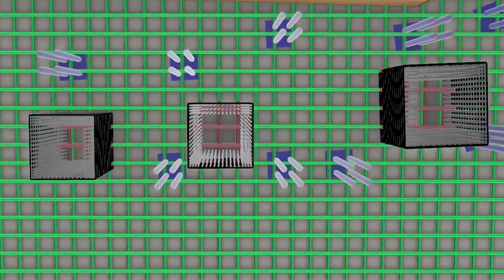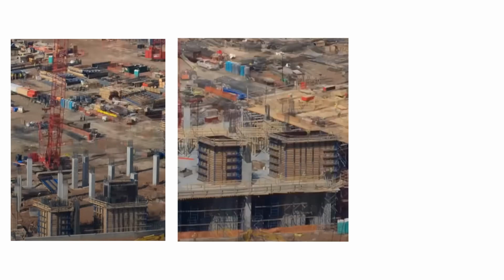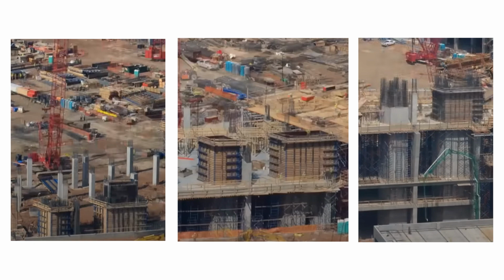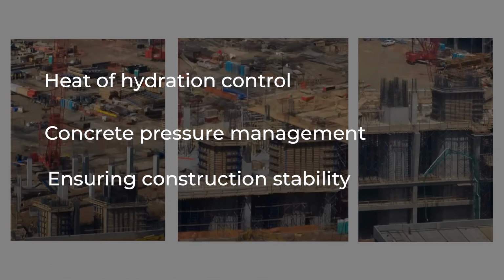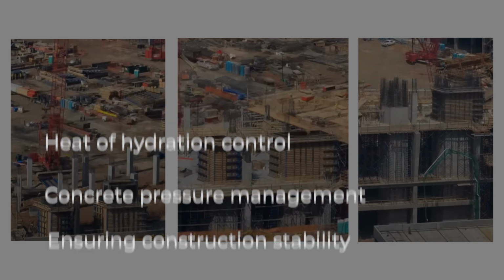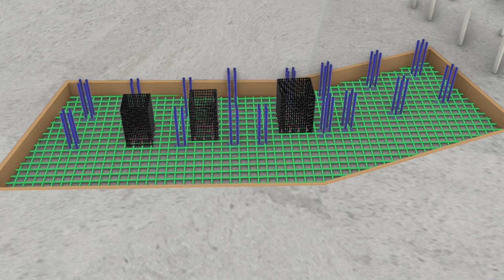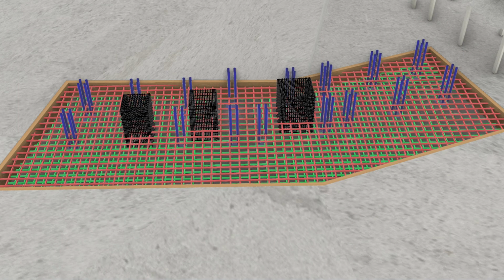for additional confinement. Instead of pouring the entire mega column at once, the structure was built in 3-meter vertical segments. This phased approach helped manage excessive hydration heat and concrete pressure during casting, and ensure safe, stable placement of large structural volumes. Each segment was cast after 24 to 48 hours of curing the lower portion.